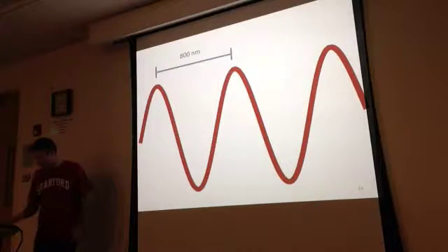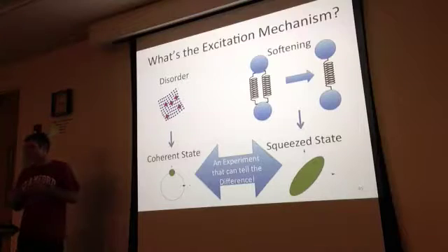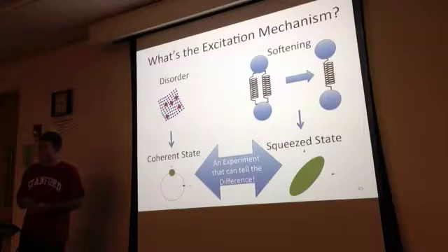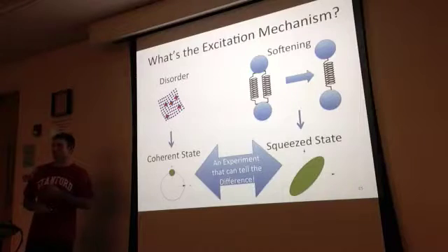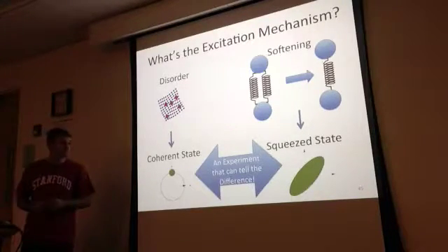So I spent some of my PhD trying to resolve this conundrum, and basically there are a couple of different ways this could happen. One is if there's disorder in the crystal, and another is if we're actually changing the force constants between the ions. And it turns out in one case you expect the phonons to be prepared in a coherent state, whereas in the other you expect them to be prepared in a squeezed state, and I'm going to explain what I mean by that. What we did was design an experiment that can tell the difference between these two, and it's going to show us that actually the right side of this picture is the correct one.